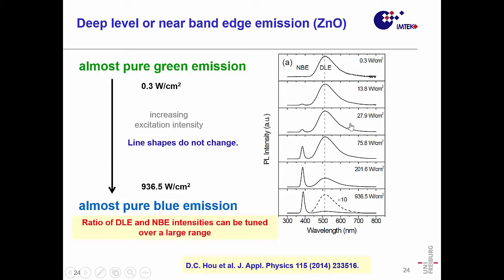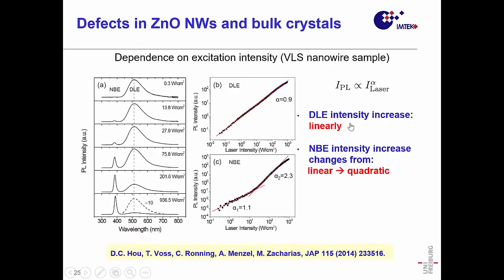Okay. So yeah, I still have my computer, so I can talk still. So what you can do is, and that is the experiment we did here, we used these wires, and we did a measurement simply changing the power density of the excitation of these nanowires. And by changing the power density, that means higher and higher power density, we simply changed the ratio, and the reason behind that is there's different physics behind. One scales linearly, the other quadratically, so you can change that as you want.